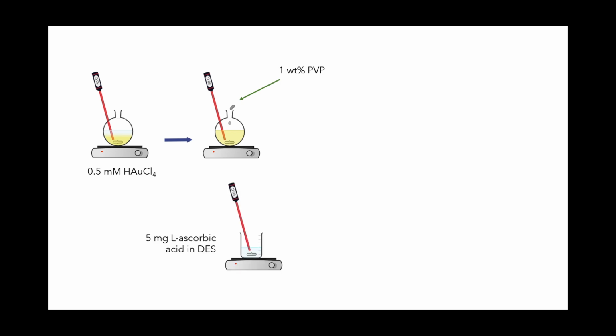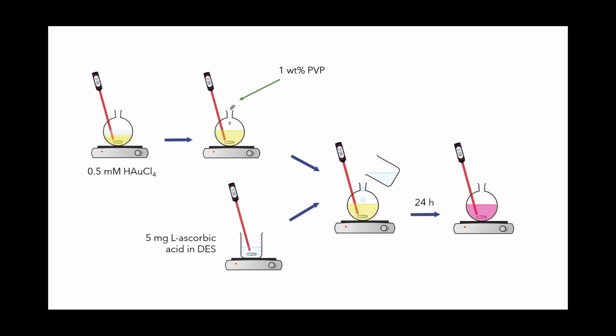Simultaneously, 5 milligrams of ascorbic acid were heated in DES. Once the PVP was dissolved into the deep eutectic solvent, the ascorbic solution was added to the gold precursor and PVP. This was left with heating and stirring for 24 hours until the solution coloration changed to pink.